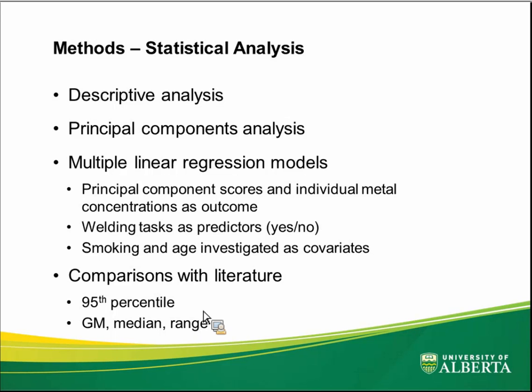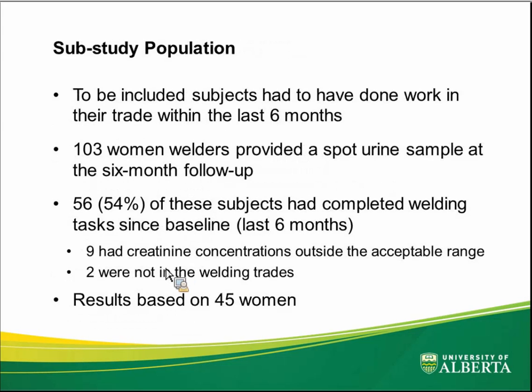And we did do a few different things statistically with the urine concentration data. We did basic descriptives. We did do a principal components analysis, and I'm going to present that today. It's a way to take our 7 metals of interest and find out if we can summarize them in a fewer number of variables. And we did multiple linear regression models where we used the component scores from the principal components analysis as our outcome variable. And then we also did it again using individual metal concentrations as the outcome variable. And our predictor of interest here was the different welding types. And we included smoking and age where they were significant, and that was actually only in the case of cadmium, but we looked at it for all of them.